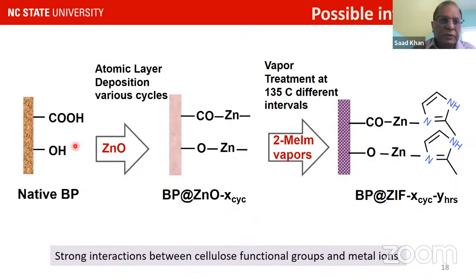And when you do that, the beauty is not only the structure of the banana paper, but the many functional groups that the banana paper has make it very conducive to grow things on it. When you use the zinc oxide for ALD, we can easily have the zinc associated with it, and then the MOF can grow on the zinc to give the banana paper MOF composites. So we're taking advantage of a couple of things. First, it's a natural material. Second, it has a nice porous structure, and third, it offers a lot of functionality to do functional treatment and get the product that we want.